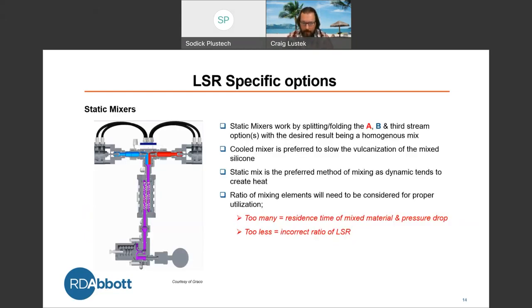As we talk about static mixers, this is where our A and B are coming in, as you can see by the picture on the left. This allows A and B to come in and we're getting a good homogeneous mix. Static mixer is the preferred method versus a dynamic, as the dynamic tends to create heat. But as I stated, we want to specify this out properly for the size. Too many, you know, we've got a residence time.